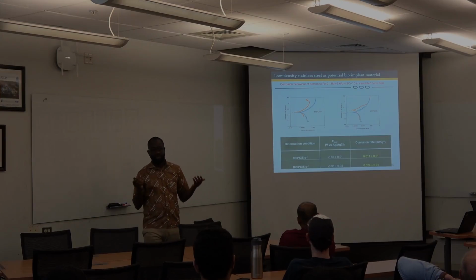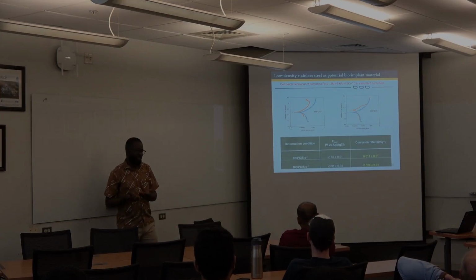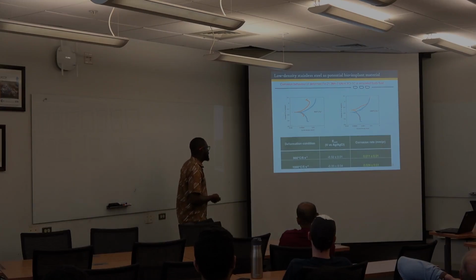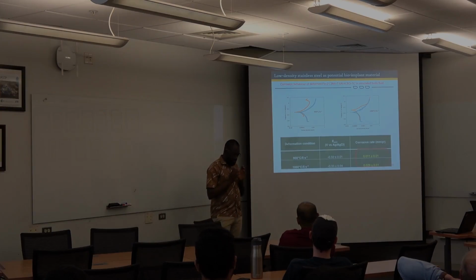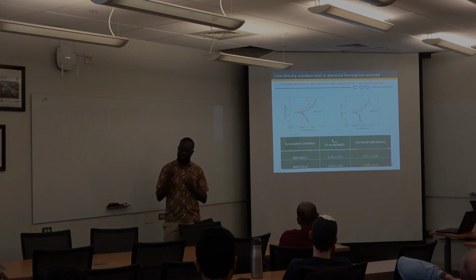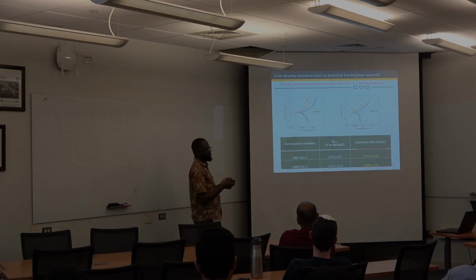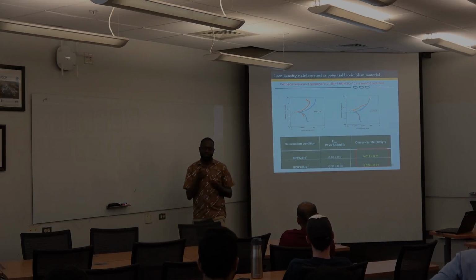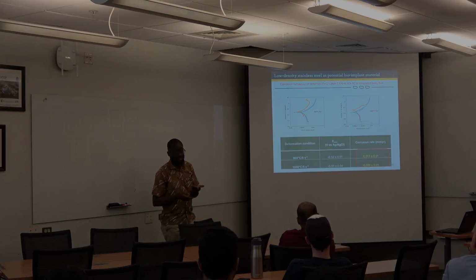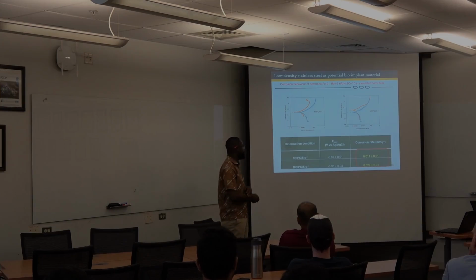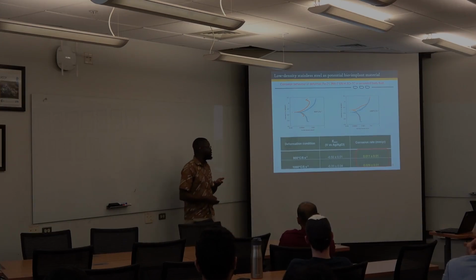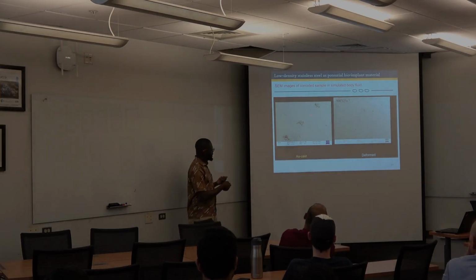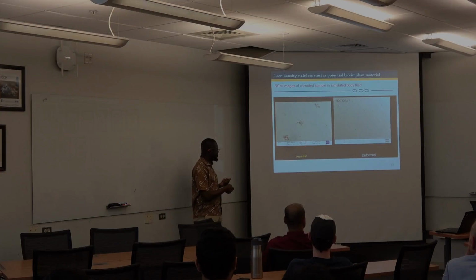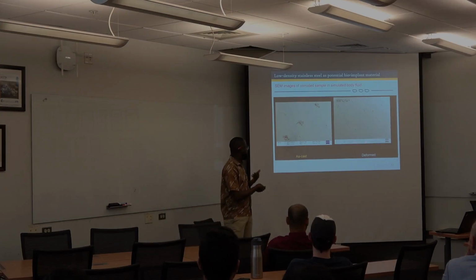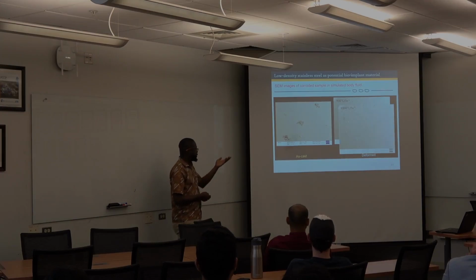So this got me confused, and I was like, okay, I need to start talking to people who probably understand this more. And this is one of the reasons why I'm here. So the first question is, how is 3 to 5% of chromium very effective in slowing down corrosion rate? And the second is, even after getting rid of the dendrites, the corrosion rates didn't reduce further. So I don't understand that. But that's the preliminary result that we've gotten now. And for our experiments, we repeat at least 3 times. So this is just to show you the pits in the as-cast, magnification is 100. And you can see that in terms of pitting, that's different, basically.